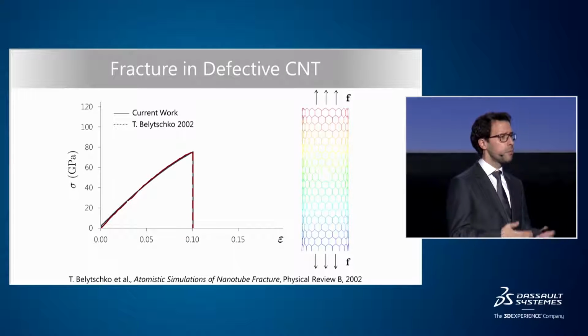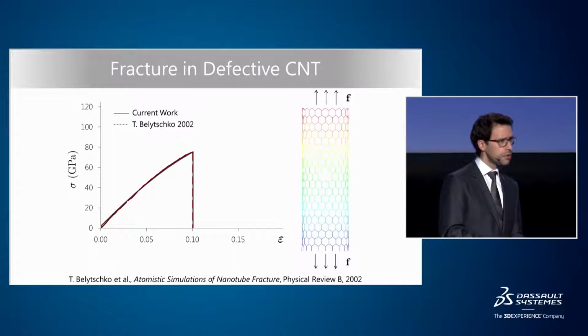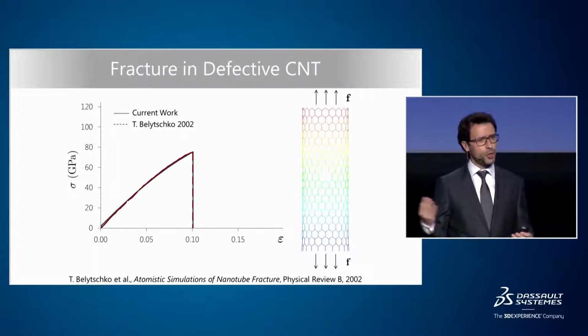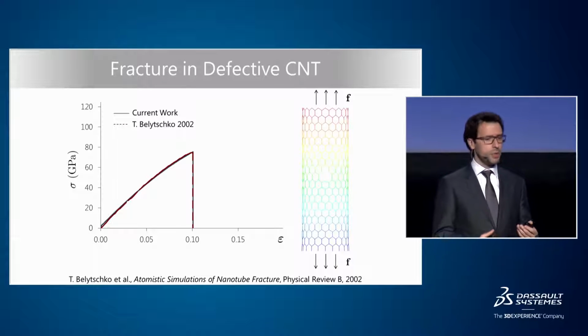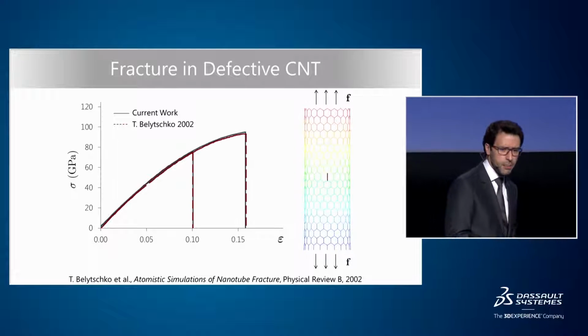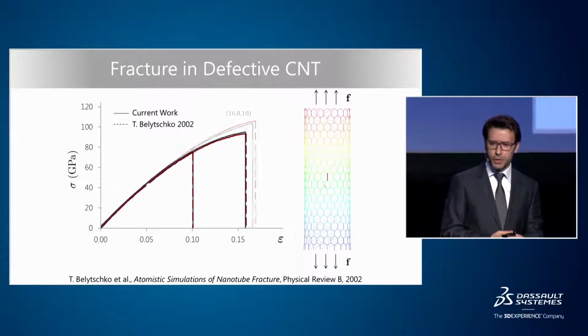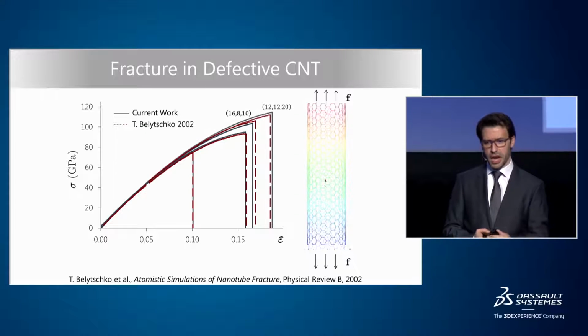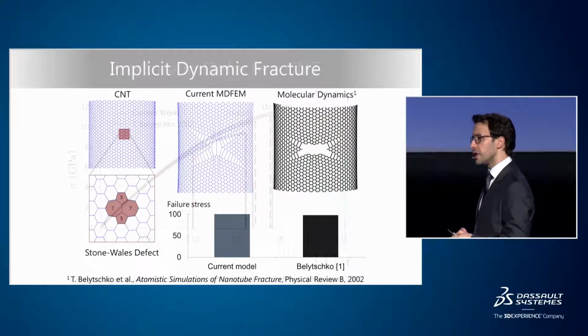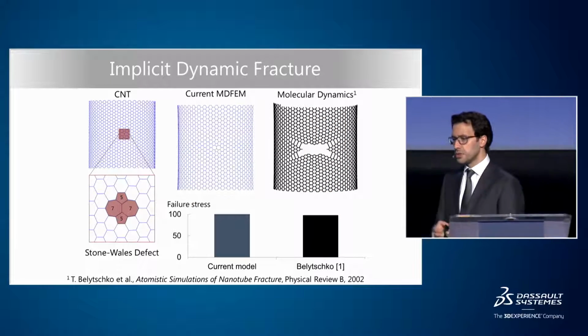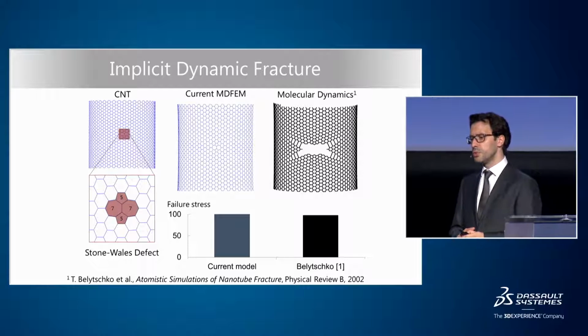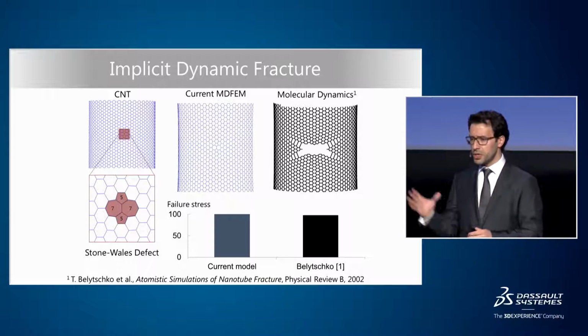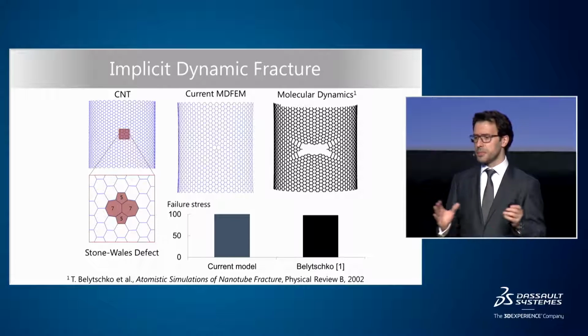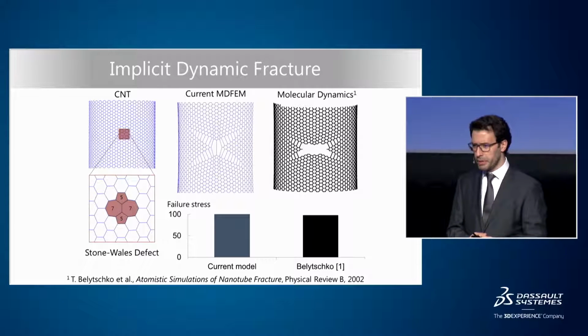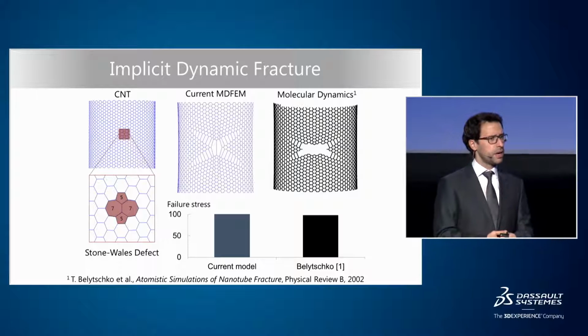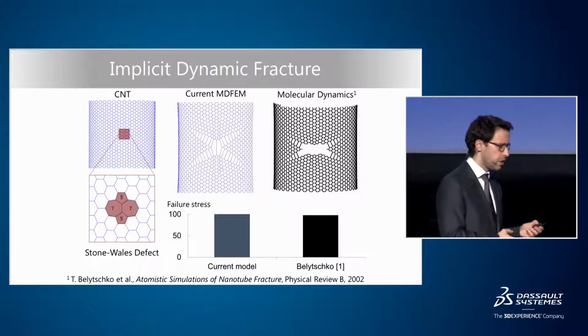So if we try to compare our solution with other results in the literature, for instance, a carbon nanotube loaded in tension until it breaks, we get exactly the same solution as molecular dynamics for different types of defects in the nanotube and also for different chiralities. If we look at the failure process, this is a carbon nanotube with a Stone-Wales defect. Our simulation is the one that you can see in the center, and it's being loaded slowly. You'll see the failure appearing, and we get exactly the same failure pattern as you get with a pure molecular dynamics code.